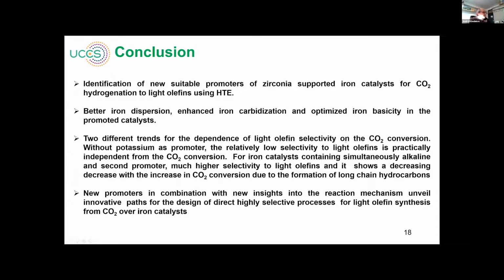So now I would like to go to the conclusion. What we obtained in this work: we identified new promoters for zirconia supported iron catalysts for CO2 hydrogenation, and we conducted a significant amount of catalytic tests using a high throughput experimentation approach. And what we found is which parameters can be improved in the most selective catalyst.